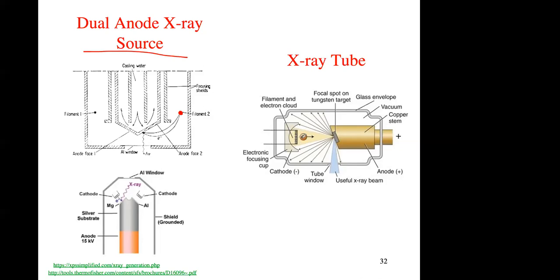So you have emission of electrons, but then between this wire and the anode, you apply a voltage. It could be higher than 3 kilovolts, for example. And depending on the energy will be the emission. Then those electrons collide with the sample, and then you have emissions of X-rays. And that's what you see here, emissions of X-rays. So you have a small window here to protect your anodes and X-ray source.